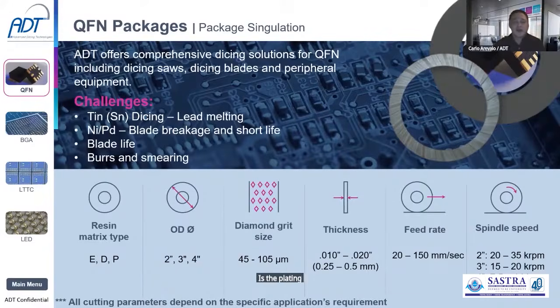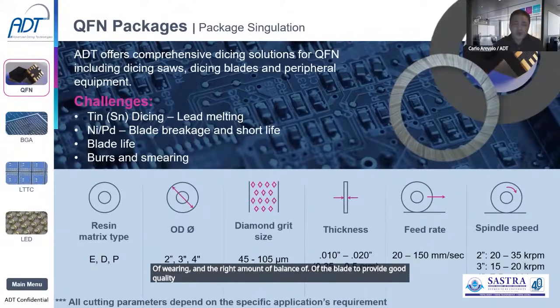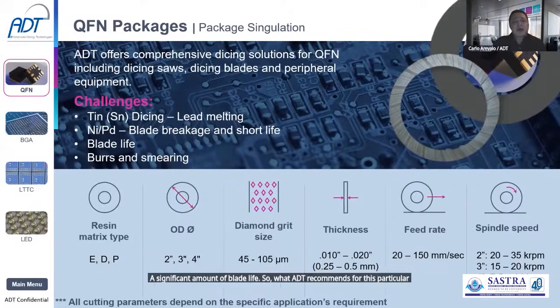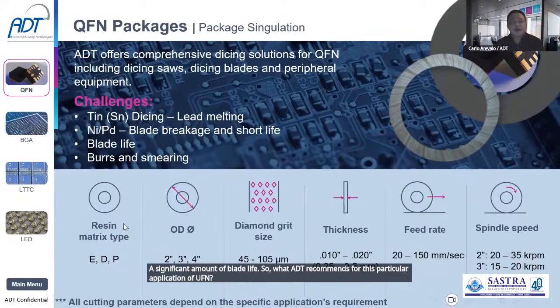Some of the things that are giving challenges to this particular package is the plating of each of the QFN packages. There is specifically tin plating in the process, or also nickel palladium plating, which is giving so many problems to the blade. So it's very important to have the right balance of wear of the blade to provide good quality and a significant amount of blade life. So what ADT recommends for this particular application of QFN is a resin blade.